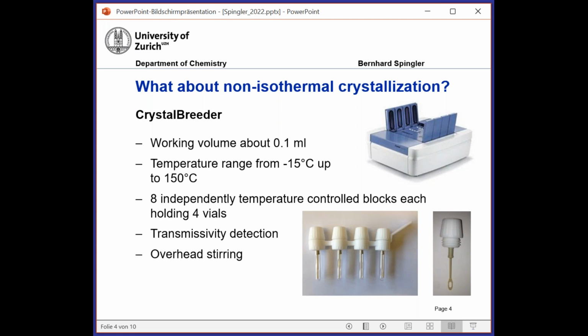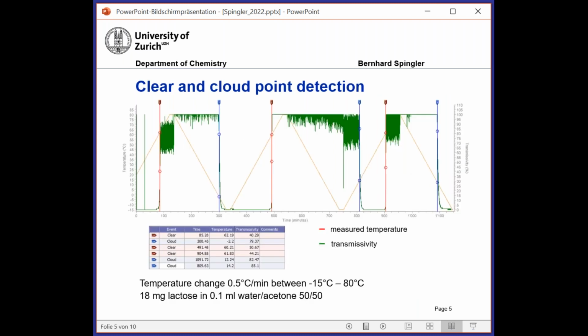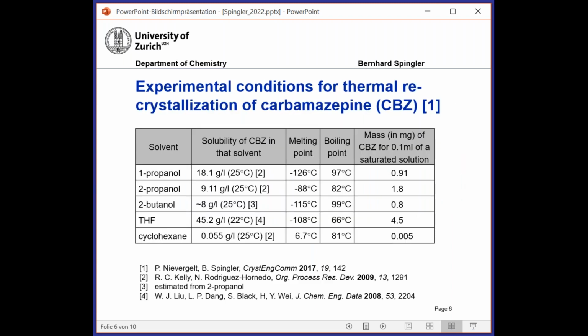This can stir, or when we want to do crystallization, obviously we can switch off the stirring so that undisturbed crystallization takes place. We were fascinated by this machine because it allows this small working volume of about 0.1 milliliter, and thereby you don't need so much material in order to do these crystallization setups. First, we tested it, and it worked very nicely in these indicated settings, just to see whether we could detect clear and cloud point for a standard system. Now let's go right away to the crystallization.